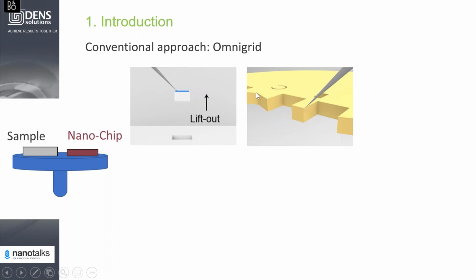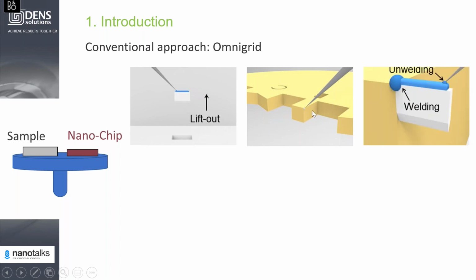Afterwards, the lamella is transferred to the OmniGrid, and you weld the lamella, release the manipulator, and at this stage you mill down the lamella to the desired thickness of 100 nanometers or less. After this step, since the sample is prepared, you need to transfer it from this point to the nanochip. But in this geometry, it's simply impossible. In this case, the lamella will land perpendicular to the surface of the nanochip, while we need it to be parallel.